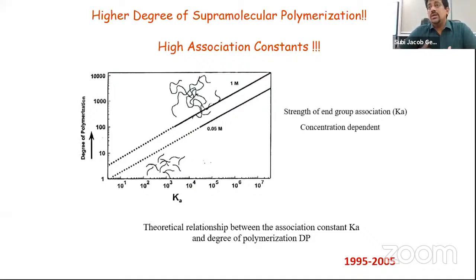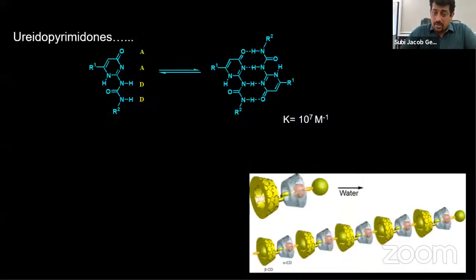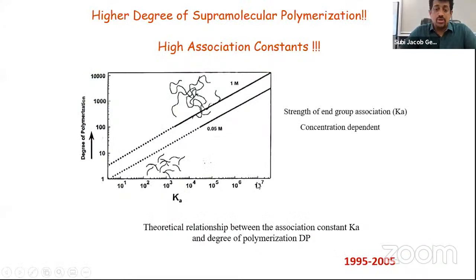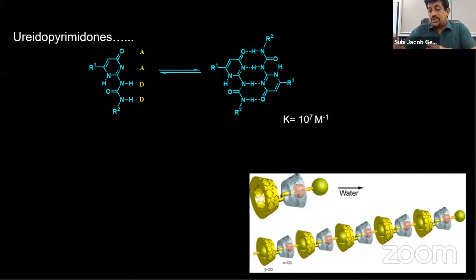We need to identify self-assembling groups or non-covalent interactions with high strength so that we can make a high degree of polymerization or high molecular weight. This has been solved by many organic chemists, and they came up with hydrogen bonding groups like this, called ureidopyrimidinones, which have an association constant of 10 to the power 7. And you see that with an association constant of 10 to the power 7, you can get an appreciable degree of polymerization in your material. Later, people realized that it's not only hydrogen bonding that is required. You can also think about host-guest interactions like cyclodextrin. Host-guest interactions can also be tuned to make this kind of extended assemblies.